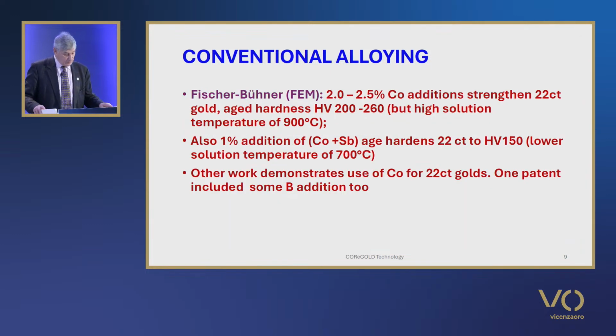Fischer-Bühner, when he was at FEM, has demonstrated the use of circa 2% to 2.5% cobalt additions to effect significant strengthening of 22 karat gold with aged hardnesses of 200 to 260 Vickers, although this involved a relatively high solution annealing temperature of 900 degrees Celsius. And he also showed that a combination of cobalt and antimony, in total 1%, resulted in a hardness of circa 150 Vickers after aging, but using a lower solution temperature of 700 degrees.